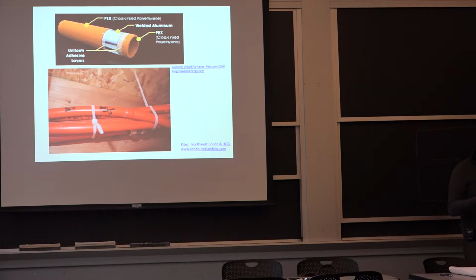And what I mean by complete deterioration is you have the polyethylene, you put antioxidant in it, and it doesn't react until you completely eliminate those antioxidants. So it's a little bit like wine that turns to vinegar. It's all good until you reach a certain point where there's no protection anymore, and you really start degrading. So it's unfortunate.